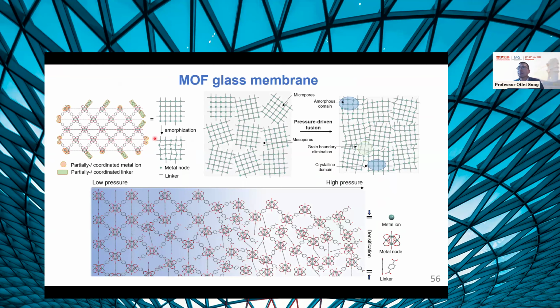We developed a pressure sintering method to pelletize this MOF monolith into dense glass-like heterogeneous MOF pellets. Initially this MOF contains mesopores, but after pelletization, we can remove these mesopores. At the same time, we also densify the MOFs, and some of the MOFs will become amorphous. This is a visualization to show the amorphization of the MOFs.